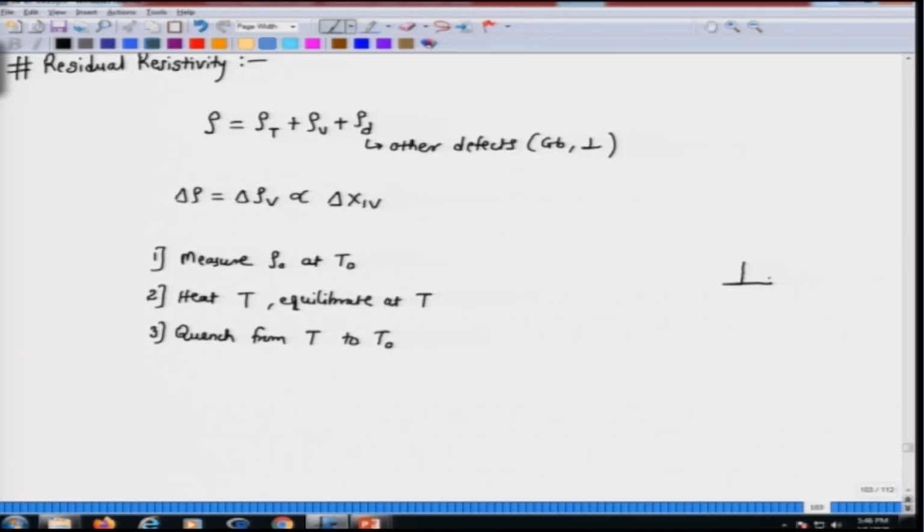For example, if there is a dislocation and a vacancy has to be created, an atom from the crystal will jump into the dislocation, and a vacancy from the dislocation will make a reverse jump and be introduced into the crystal. This is the way a vacancy is created. Similarly, grain boundaries or surfaces can act as sources of vacancies when we heat the sample to a higher temperature.